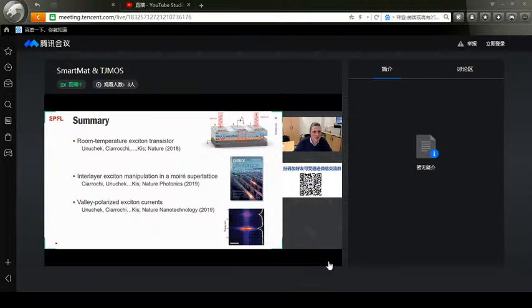So at this point, I would just like to summarize, since we're running out of time. So I showed you the demonstration of a first room temperature exciton transistor based on 2D materials, how we also can manipulate exciton energies and polarizations in a Moire superlattice, and finally how we realized valley polarized exciton currents in a heterostructure where we managed to decrease this Moire coupling.